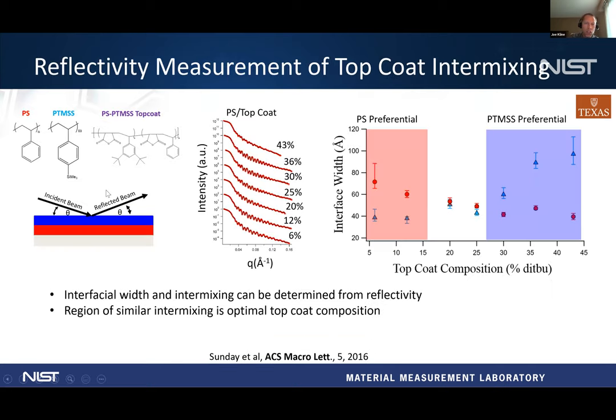And in doing that, you can see here, this is a particular case of polystyrene. These are the different reflectivity curves and the fits that you have on there. From this fit, you get an interfacial width between the top coat and the homopolymer. On the red side, the red ones here are the polystyrene, and the blue ones are this PTMSS. In this particular one, as you get lower concentrations of the t-butyl group, you can see it gets sharper, and that means they don't like each other as much. Similarly with the polystyrene, it's opposite. And in the middle here, where they both have about the same interfacial width, is where you have a neutral surface that makes the block copolymer stand up.